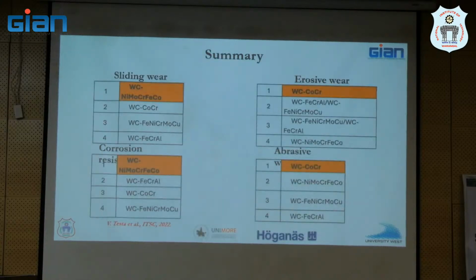This is a little complicated slide, but if you look at the summary, depending upon what kind of surface degradation you are talking about, some of these are even better than the tungsten carbide cobalt chrome, which is the reference material. In some cases, they are almost as good.